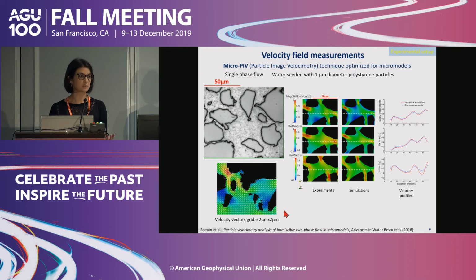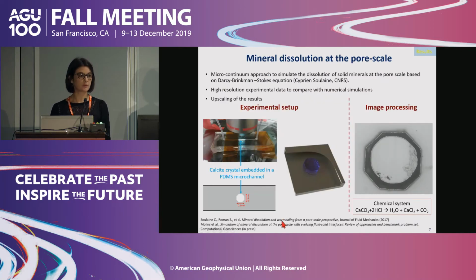So then with these techniques, we can explore much more complex cases. Today I will focus on the use of microfluidic experiments to study mineral dissolution at the pore scale. A micro-continuum model has been developed by Cyprien Soulaine, based on the Darcy-Brinkman-Stokes equation, to simulate the dissolution of solid minerals at the pore scale. The idea was to investigate how the flow will change due to dissolution. This approach was presented yesterday by Sergi Molins because it is part of a benchmark effort. And to validate the numerical model, we needed high-resolution experimental data to compare with the numerical simulation.